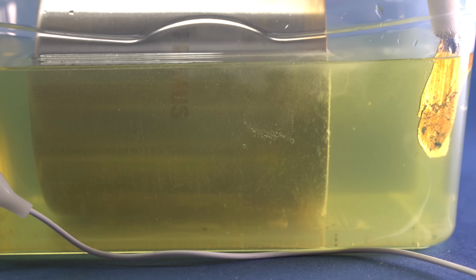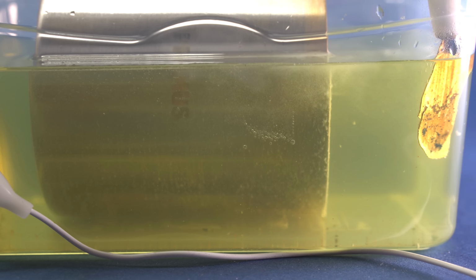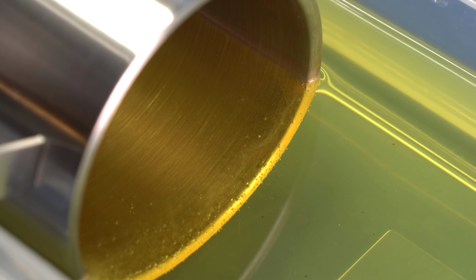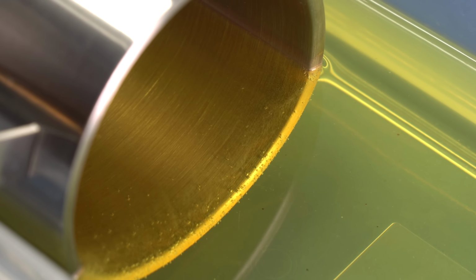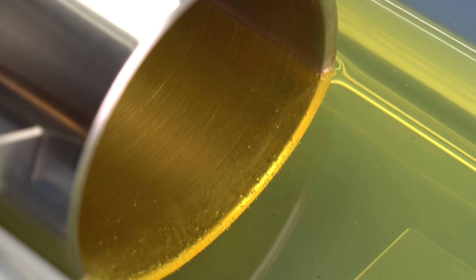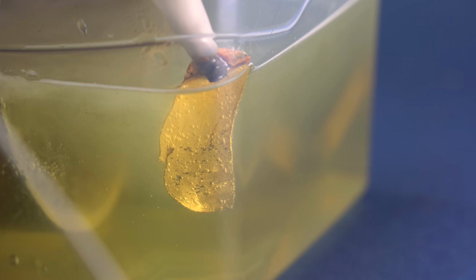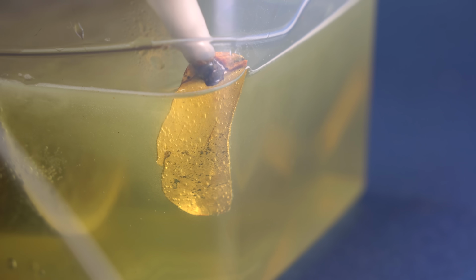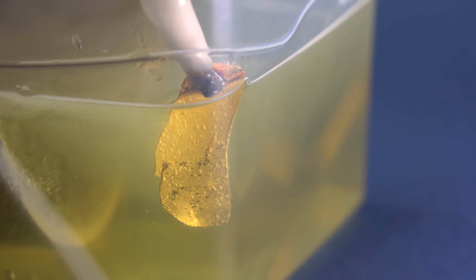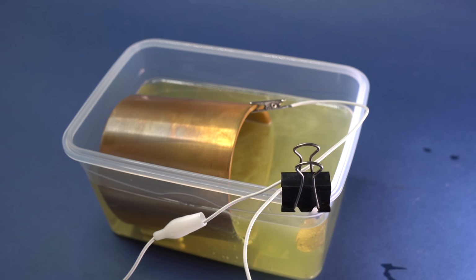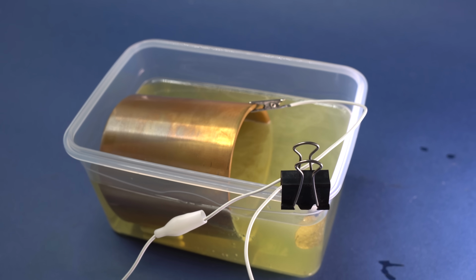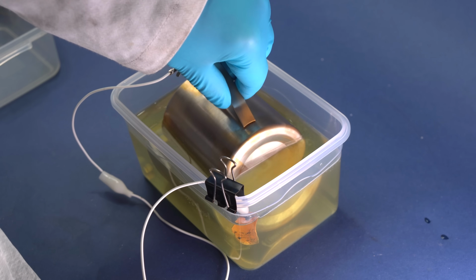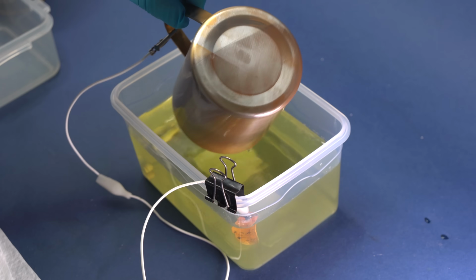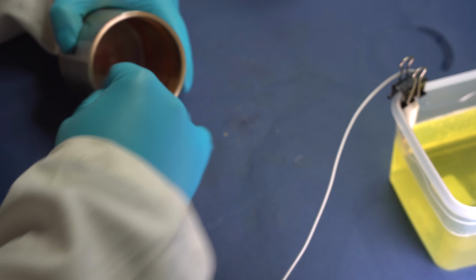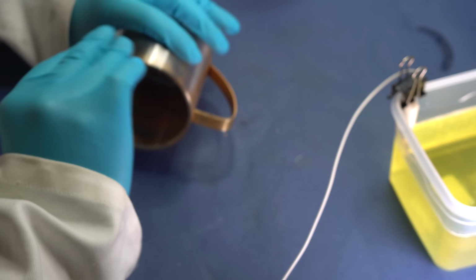When current is applied to the electrodes, pure gold is deposited on the cathode, which is our cup, and also on its surface hydrogen is being released. Along with that, oxygen is being released on the anode, which is why it is bubbling with oxygen. After 1 hour, I noticed that this method of gold plating doesn't coat evenly, even if the cup is constantly rotated. That is why I evened out the gold plated on the cup with steel wool.